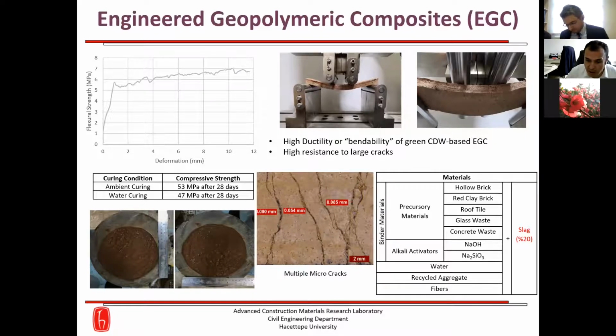As you can see here, even at ultimate load, the crack width remains 100 micron. This tight crack width is self-controlled, remains less than 100 micron, and whether the composite is used in combination with conventional reinforcement or not, it is a material characteristic independent of the rebar reinforcement ratio. But in the case of conventional reinforced concrete, it relies on the steel reinforcement for crack width control. This will provide us a significantly higher durability performance because of the high ductility and crack healing or sealing properties during exposure to the atmosphere.